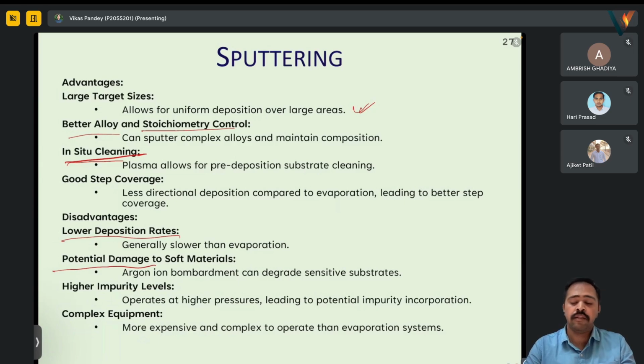Like I said, although we are going to lower pressures, that is very high vacuum, the real operation occurs at a higher pressure, say 10 to the power minus 2, minus 3 range. That's why there can be impurity levels higher compared to an evaporated thin film. The equipment is much more complex compared to thermal evaporation. In thermal evaporation, it is simply a transformer to step up the current, and we have the boat and the vacuum systems.